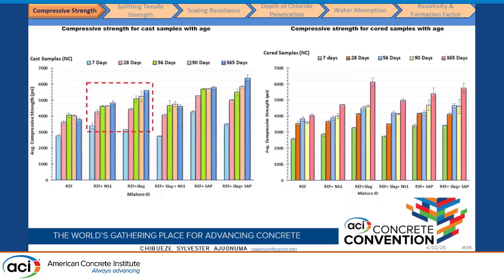So the latent hydraulic property of slag came into effect, especially at a later age. But the addition of SAP, if you notice the last bar, helps also to compensate for the loss in early age strength for the mix with slag and SAP. A similar trend was also observed for the mixes with slag, for the cores extracted from the field.